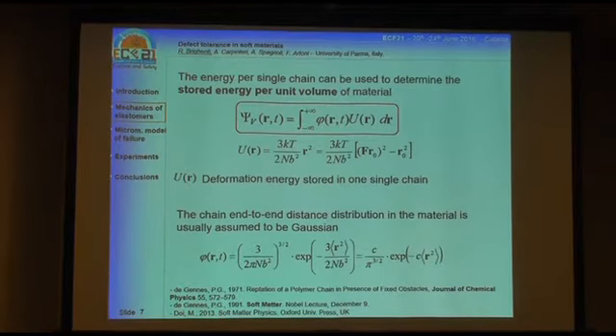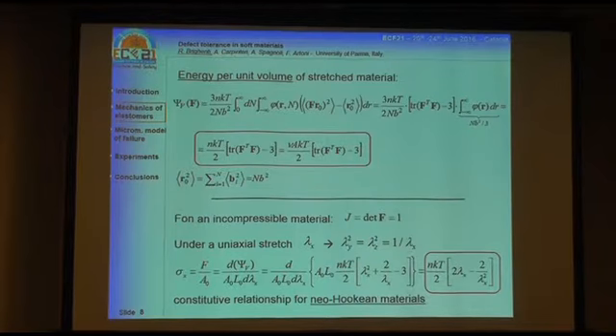And finally, this is the standard Gaussian distribution which is used for polymers, where we have all the parameters I mentioned before explicitly written here. So the energy per unit volume can be easily obtained by integrating the above expression. We can have a final equation that gives us the value of the energy per unit volume, and that depends, of course, only on the deformation tensor F that we are applying to the material.